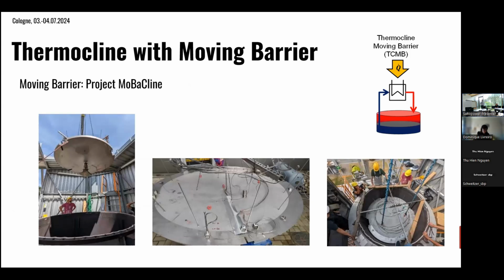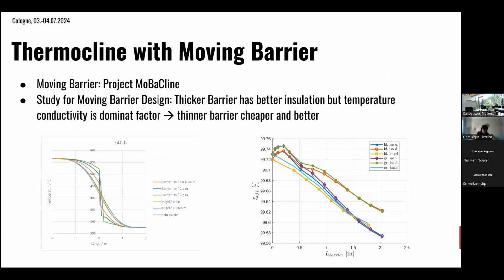And then we had a project which was called MoBaCline, where we tested the moving barrier concept. So here are some pictures of this moving barrier during the commissioning. We did a lot of theoretical work initially. On the left, you can see, for example, a standby simulation. Obviously, if you have a thicker barrier, which has more insulation, then there is less heat transfer through the barrier. But interestingly, when you look at the storage efficiency after cycling, then we found that you have the highest efficiencies basically with smaller barriers.